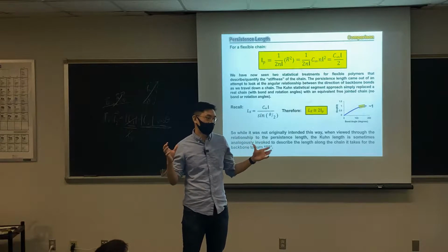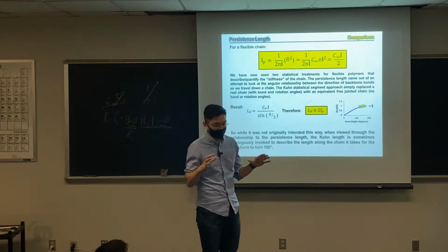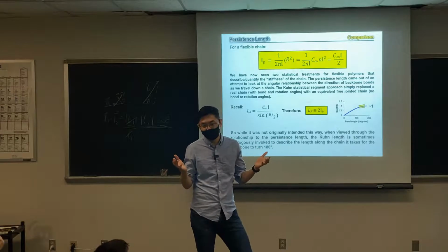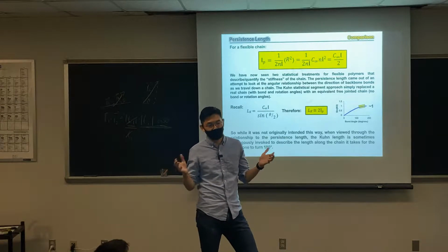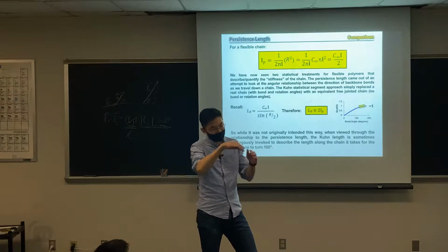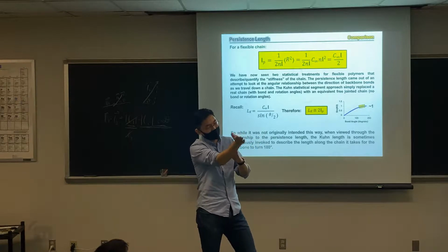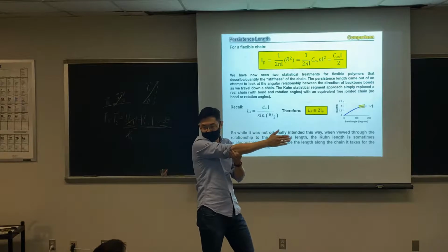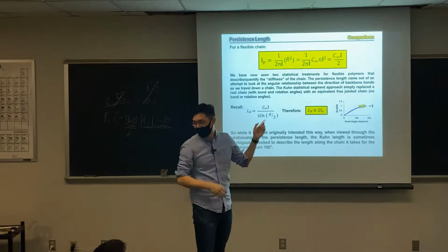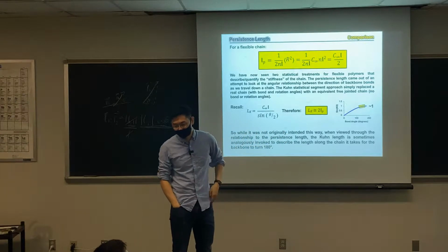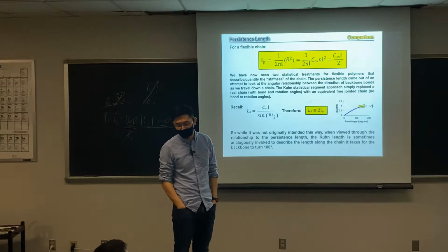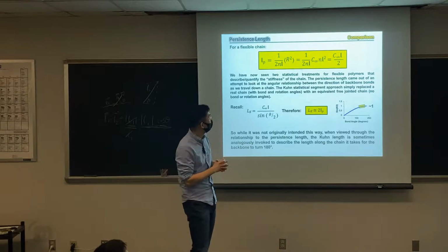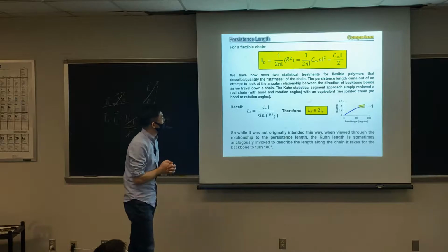Or in other words, in the expansion ratio when we talked about the free rotation chain, when the bond angle is bigger, the chain tends to point in one direction. When the theta angle is close to 180, you have a much higher characteristic ratio and persistence length. This is how everything can be tied together.